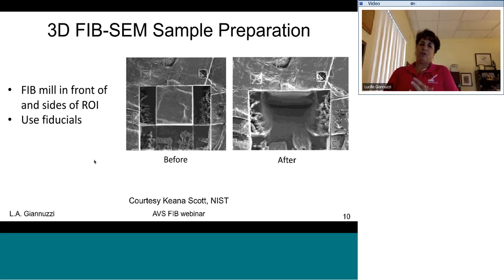Now, for 3D FIB work, there's a lot of work that goes into the initial sample setup. Because you want to avoid sputtered material redepositing on the sidewalls, you have to really open up the area. So this is from top down. This is the region of interest, okay? And so all of this material around here has been FIB milled away. So that when you continue to FIB mill and take a slice, that sputtered material will accumulate here and not block your region of interest.